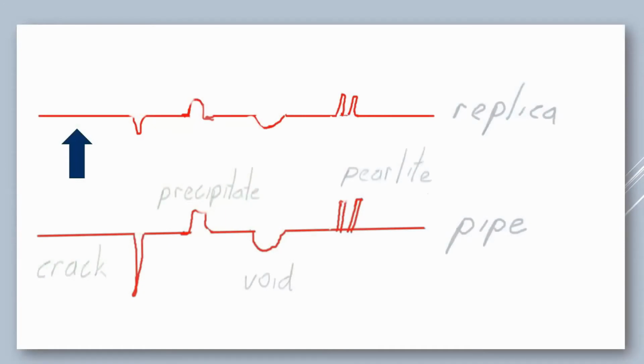So this is just a side view of looking at the pipe. I see the bottom one is going from left to right. I got a crack, I got a precipitate, a grain boundary, I got a void. And now what I do is I wet that cellulose acetate, I put it on the surface. And of course, now I'm getting a negative impression of everything that was on that surface. So a crack on the replica, with a blue arrow, comes out looking like a ridge. A precipitate is going to look like a hole. A void is going to look like a bump.